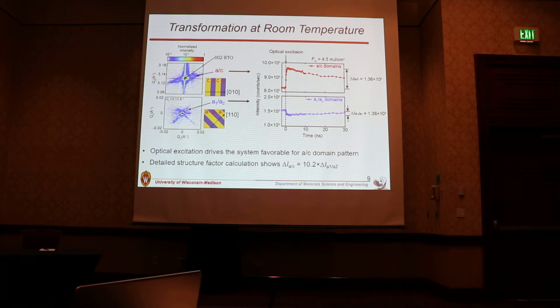So to study the transformations, we have measured the total intensity changes of the AA and AC domain diffuse scatterings. We measured the total intensity as a function of time. At time 0, the optical pulse arrives at the sample, and we observed the intensity change of AC domain patterns and also AA domain patterns. Optical excitation increased AC domain diffuse scattering, while the AA domain diffuse scattering was decreased by the optical excitation. So it's indicative of the transformation from AA to AC, but we found that the intensity change is quite